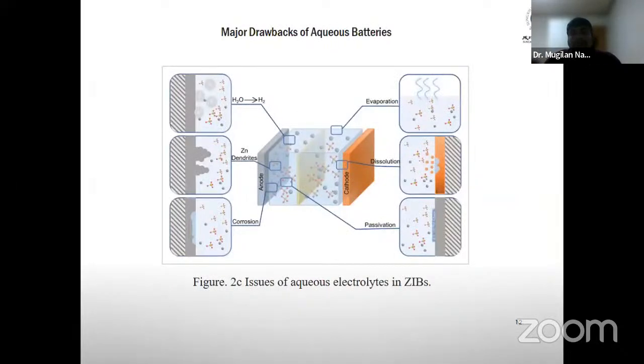What are the major issues we will find in aqueous electrolytes? Hydrogen evolution will occur on top of the anode passivation layer. It can tend to form dendrites, and it can also lead to corrosion on top of the anode. Whereas at the cathode, the electrolyte will have a dissolution problem. The ion transportation can be slower when compared to solid electrolyte interfaces, and this is an aqueous electrolyte, right? So we can also have an evaporation problem. In that, the zinc sulfate can be separated as zinc and sulfate partially. And at a high temperature, the sulfate passivation layer can be easily removed from the active layer.